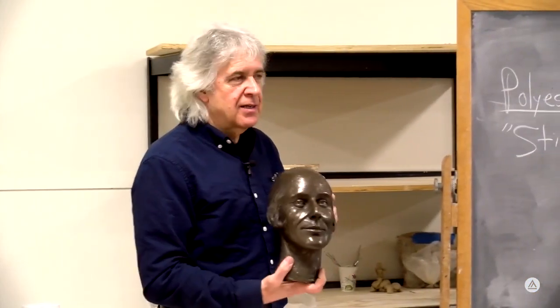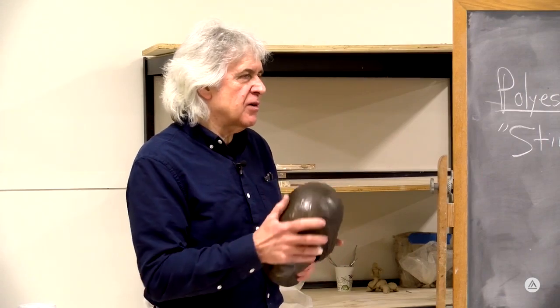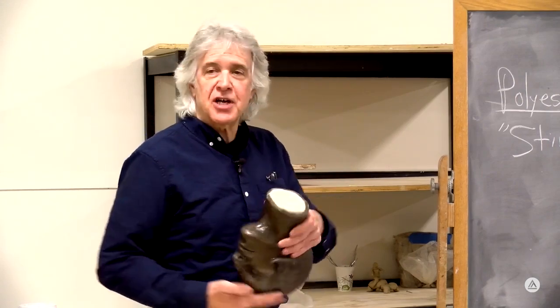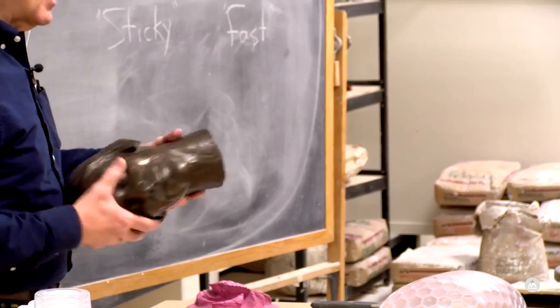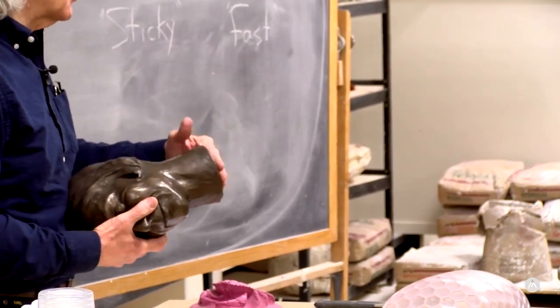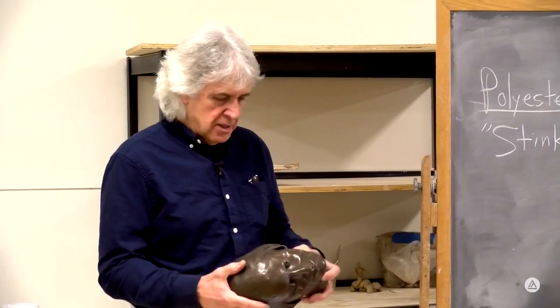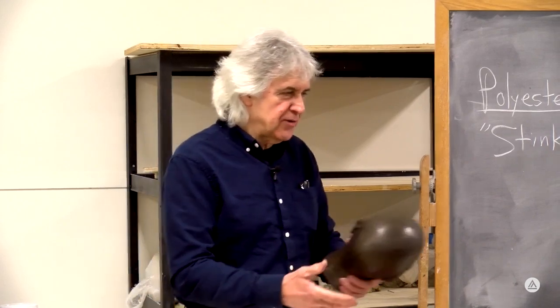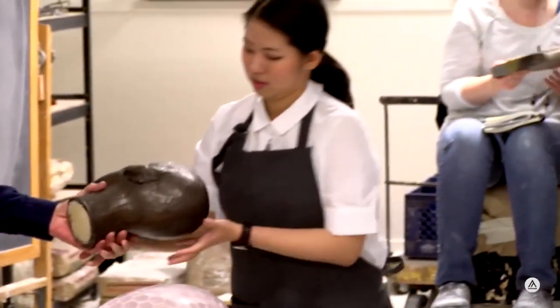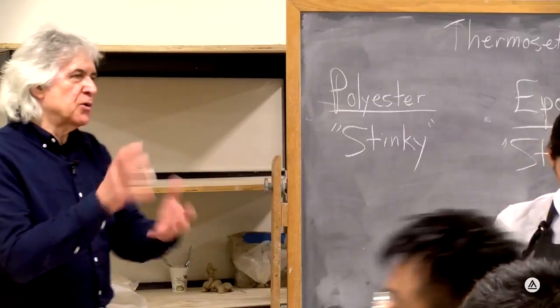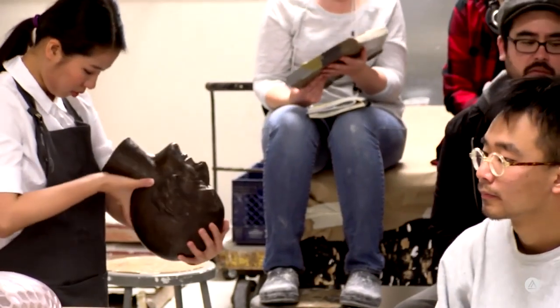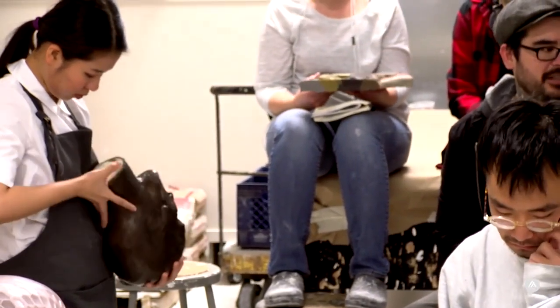So it was this type of resin that was then infused with the bronze powder, and then a layer was rotated inside the mold. So you've got a thin layer, and then it was filled with foam. So this is actually hollow. So you can pass her around. Be very careful. Don't drop her. 2 hands, please. We rotated the mold. So it was a closed mold. We poured it in, rotated around. A heavily infused bronze layer went into the surface.